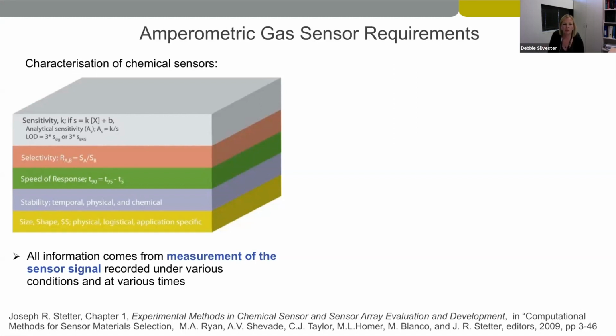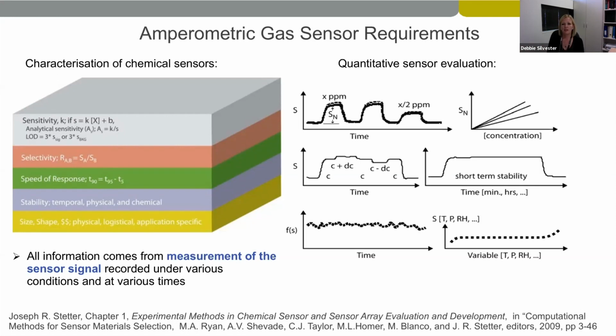And so this is important depending on the application you're looking at. You need to have a sensor that will fit in certain dimensions, and also that is cost effective to the end user. So the gas sensor companies look at all of these parameters, and they get all of their information from measuring the sensor signal under various conditions and at different times. And so they have electrodes and electrolytes, and then they have their gas of interest that they introduce at different concentrations. So the first way that they evaluate the sensor is by looking at the sensor signal or the current as a function of time when you add in different concentrations of gas. And you can then see the calibration graph on the right-hand side.